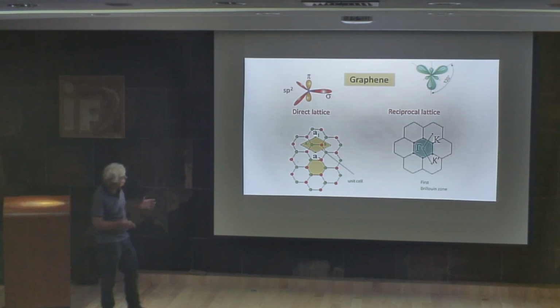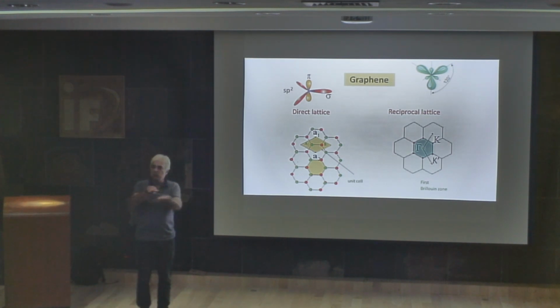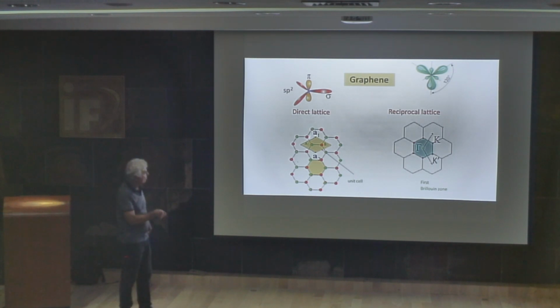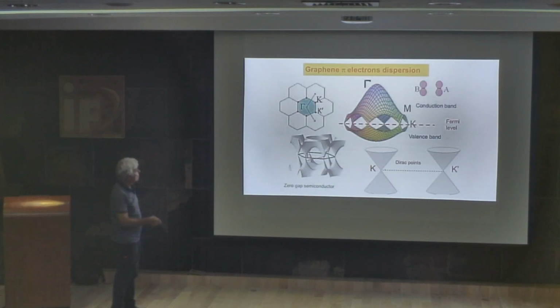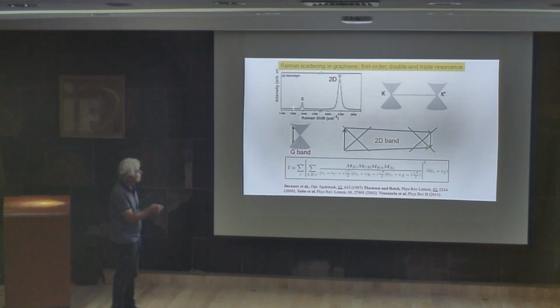But then we can consider that in graphene we have two sublattices, one formed by the red atoms and the other formed by the green atoms. And one sublattice is vibrating against the other one. It's vibrating like that, and this vibration has a given frequency. This vibration is what gives rise to the G band. Then the G band is the stretching mode of the carbon-carbon atom vibration.